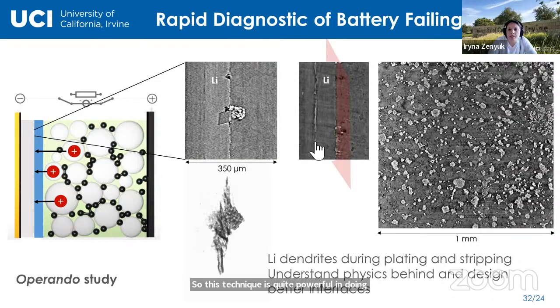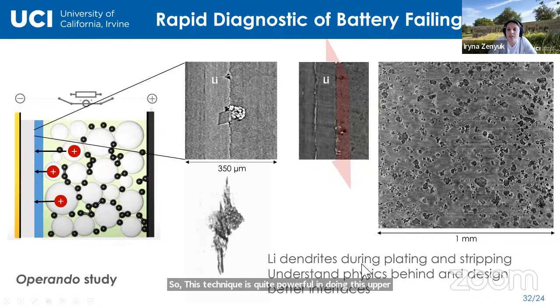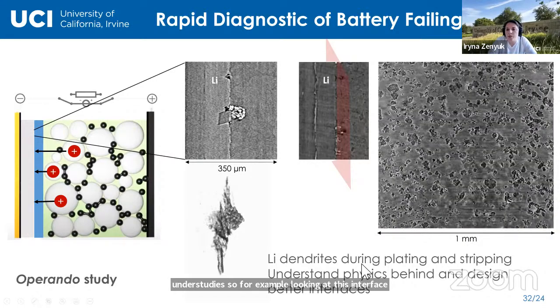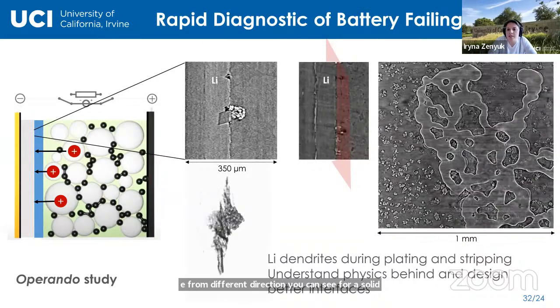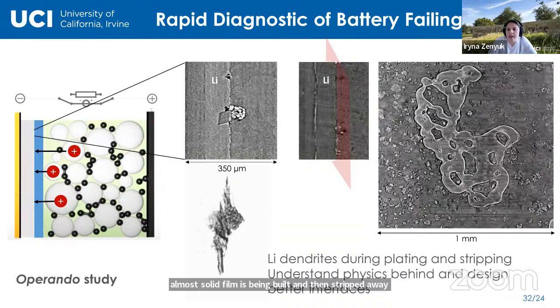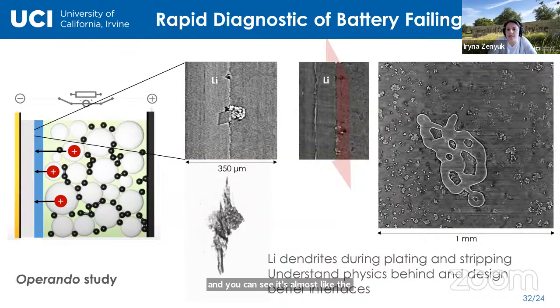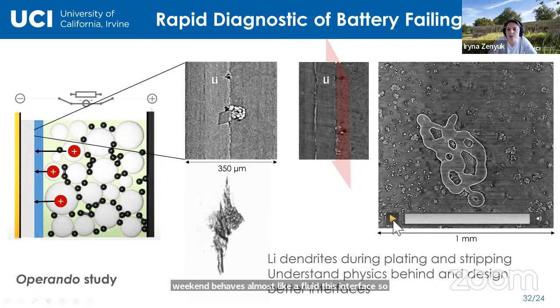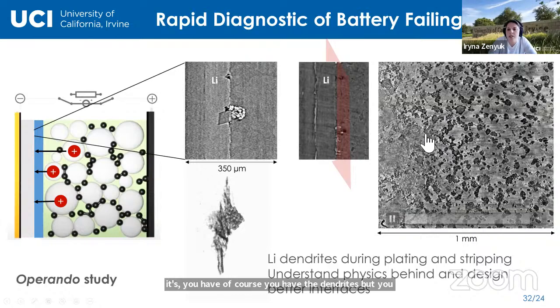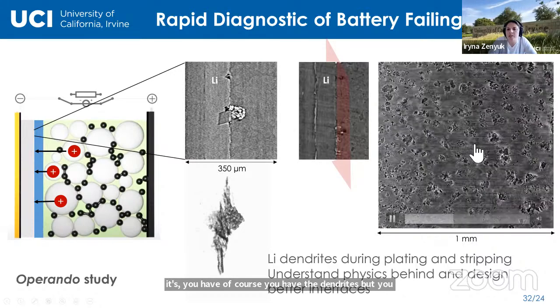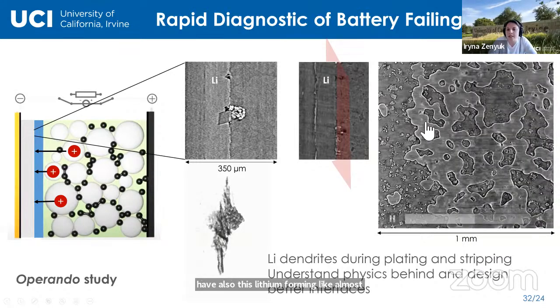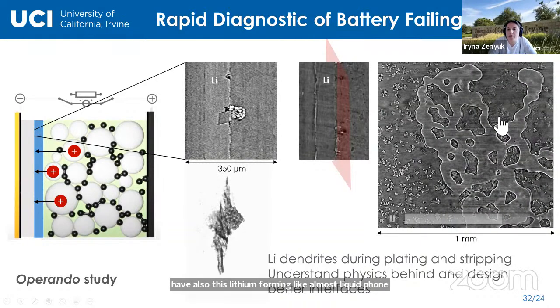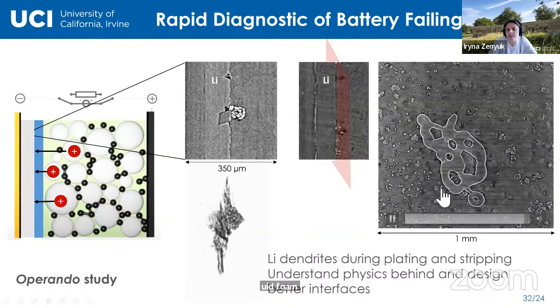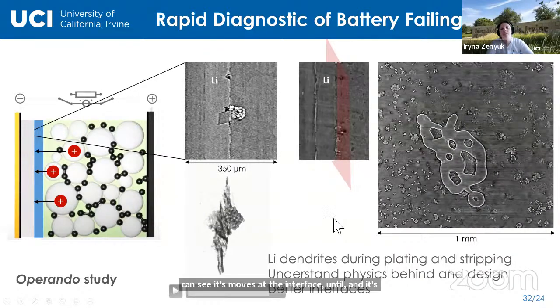So for example, looking at this interface from different direction, you can see almost solid film is being built, and then it's stripped away, and you can see the lithium behaves almost like a fluid at this interface. So of course you have the dendrites, but you also have this lithium forming almost like a liquid film. And then when you strip it back, it moves at the interface, and some of the dead dendrites are being left, and some of this film is being left. So it's a really interesting phenomenon.